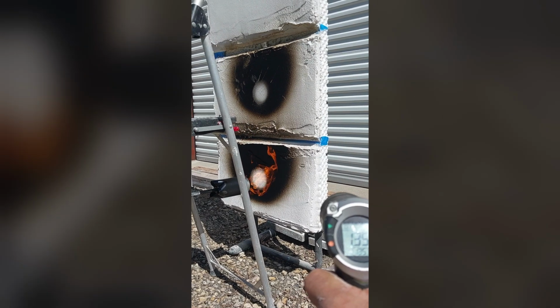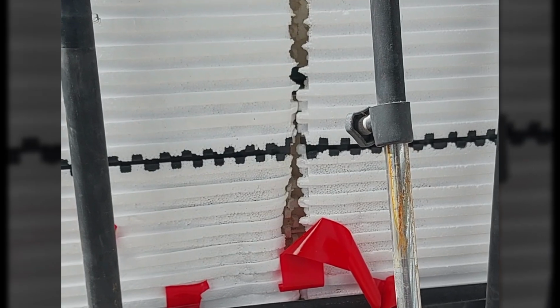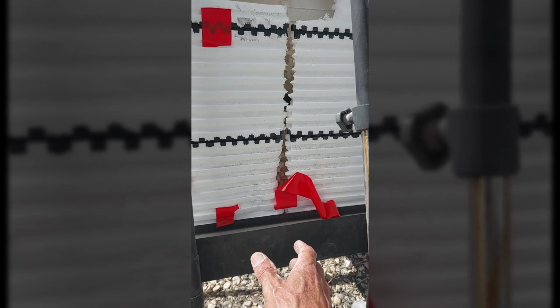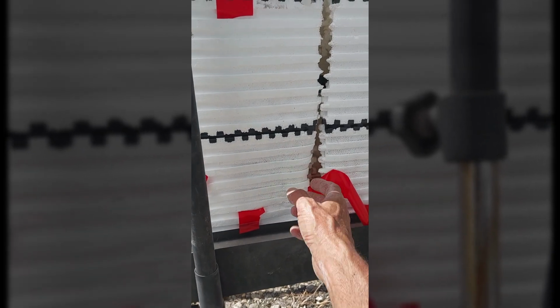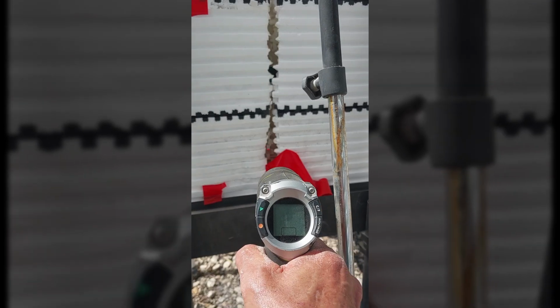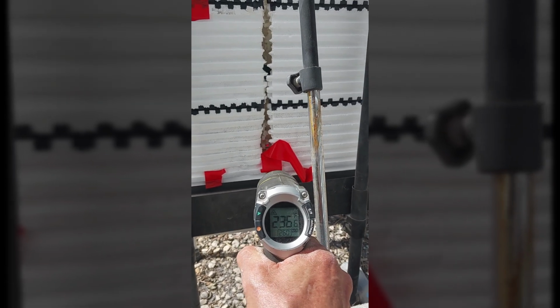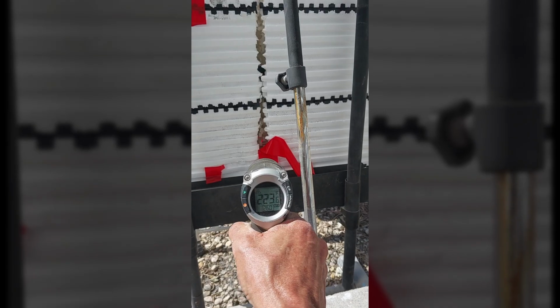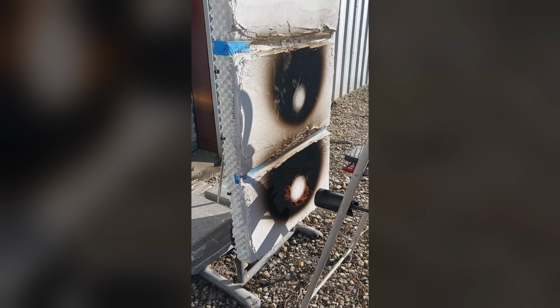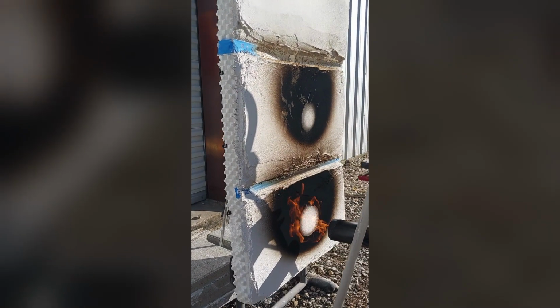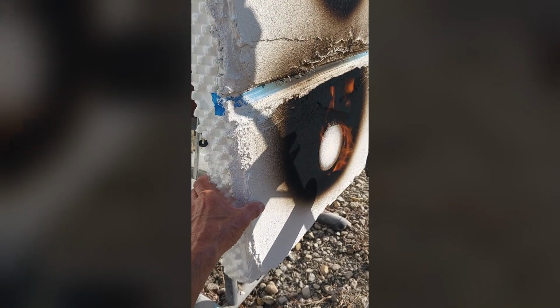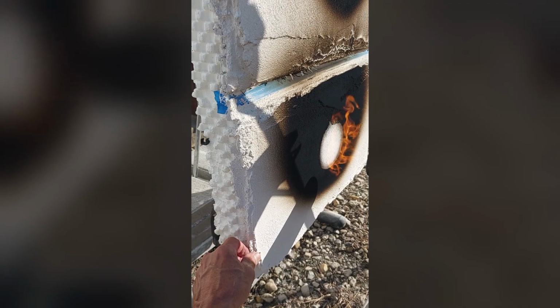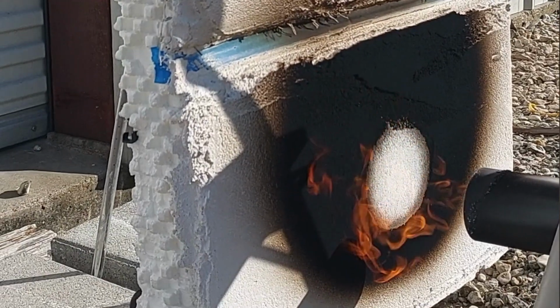At 5 hours, with the flame still burning over 2000 degrees Fahrenheit, there is no significant degradation on the backside. The red tape that was placed on the seam remains intact as well. Surface temps are stable, while the interior cavity measures from 200 to 250 degrees. We're on hour 7, and on the front side, we have no delamination whatsoever. The material remains solid and the BioLime coating is married to the ICF without any pull away or separation. The hot spot is intact and there's no material down at the ground.